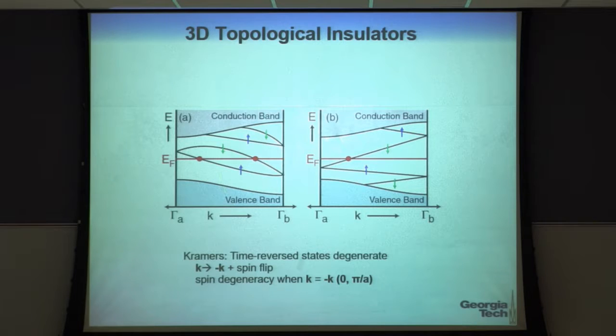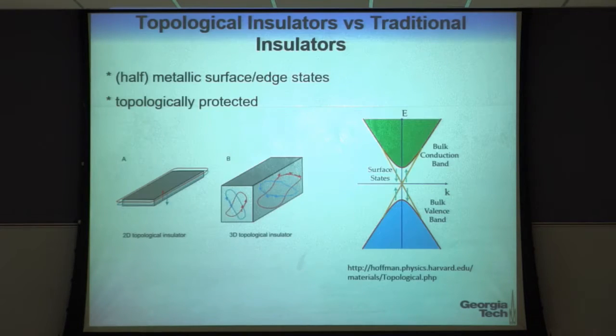This would be a trivial or normal insulator, okay? But you could have a case which would correspond to a different value of this topological, called a Z2 topological invariant. You could have a case where I get an odd number of band crossings. And in that case, I'm stuck. If there are an odd number of crossings of the Fermi energy, then in fact, I have to have a metallic surface state, okay? That's this case over here. Again, I have to have Kramers degeneracy here at k equal to 0. That's gamma, k equal to 0. And I have to have it also at pi over a, okay? So that's what happens in a three-dimensional topological insulator.